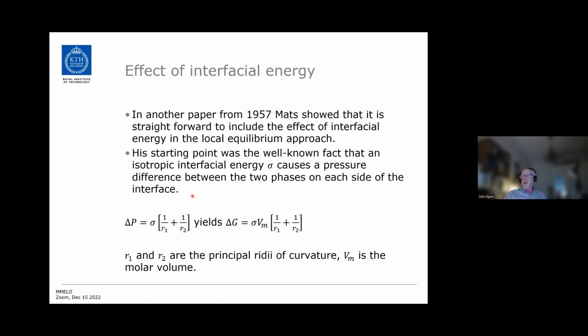In another paper the same year, Mats showed that it is straightforward to include also the effect of interfacial energy in the local equilibrium approach. He started with the effect of an isotropic interfacial energy, which causes a pressure difference between the 2 sides of a phase interface. And here is the isotropic interfacial energy, and R1 and R2 are the principal radii of curvature. And of course, by multiplying with a molar volume, you get this into a driving force.